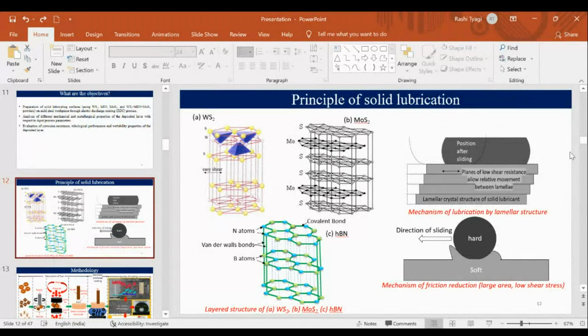So basically, before going to the methodology used in the EDC process, we want to discuss the principle of solid lubrication. See, in this figure you can see different solid lubricants, WS2, MoS2, hBN, in which it can be seen that they all have a layered structure. Layered structure means there is a laminar crystal structure, which means there is a layer by layer formation. They are composed of laminae. They can align themselves in the direction of motion.